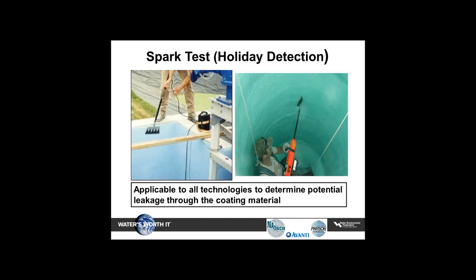Spark testing, we've talked about that. This is pretty common to all technologies. And spark testing will determine if the application has been installed monolithically. In other words, monolithically meaning there are no pinholes or defects or thin spots or issues in the coating that will cause it to prematurely fail. Those of you who are familiar with most coatings know that if a single spot on a coating begins to deteriorate and the corrosive environment gets under that coating at that point, over time that will find its way under the majority of the coating, and the coating will tend to fail in its entirety. So it's important, virtually for every technology, that they be spark tested to make sure that they are 100% monolithic and have no defects.